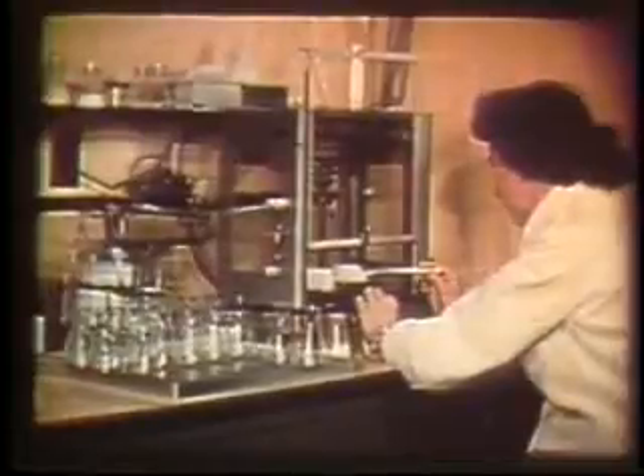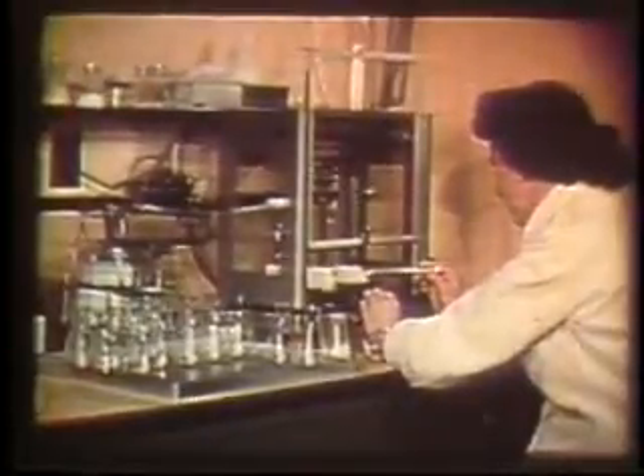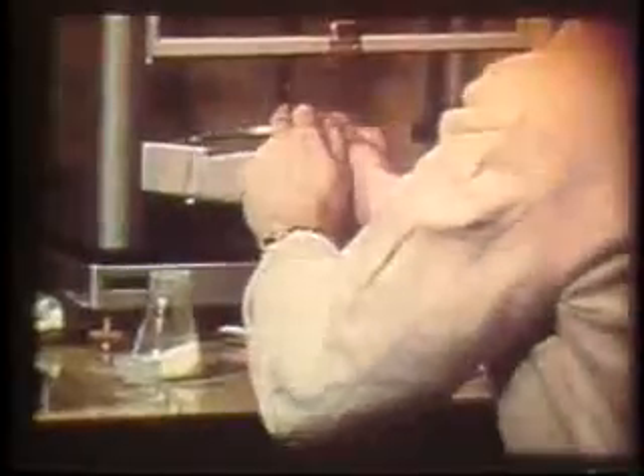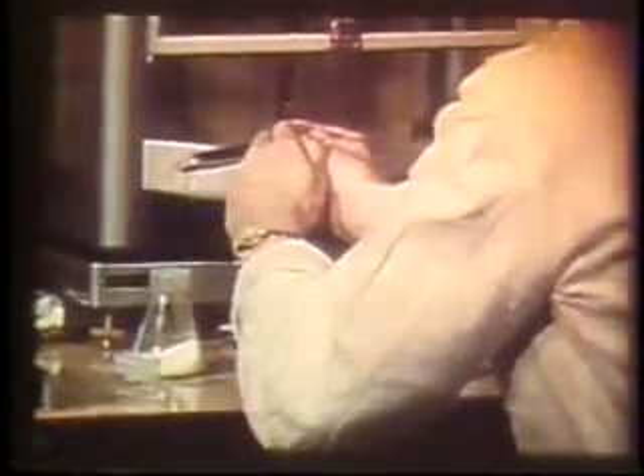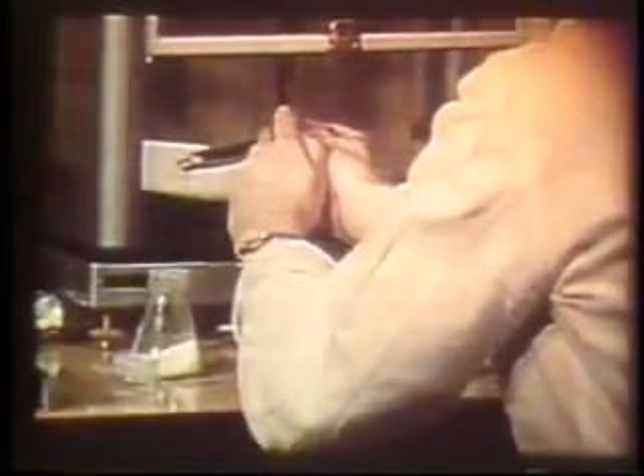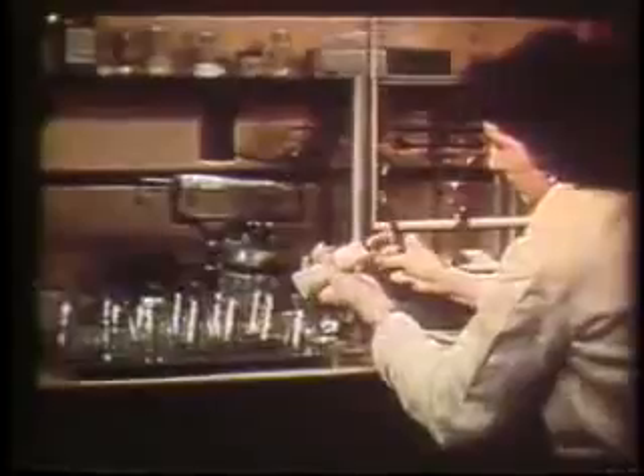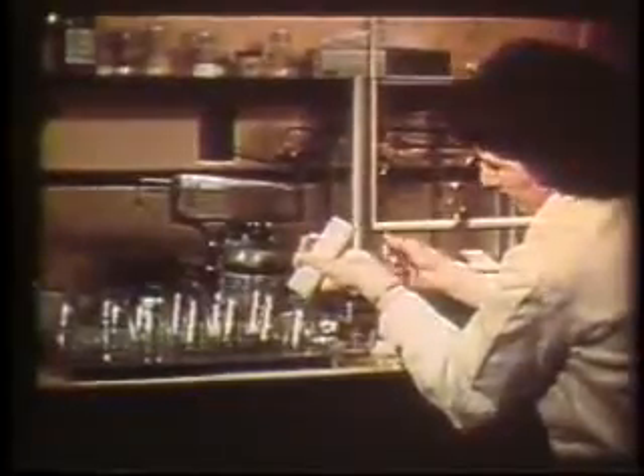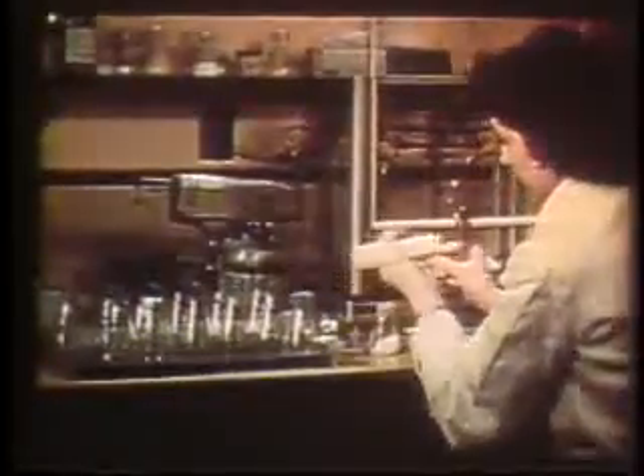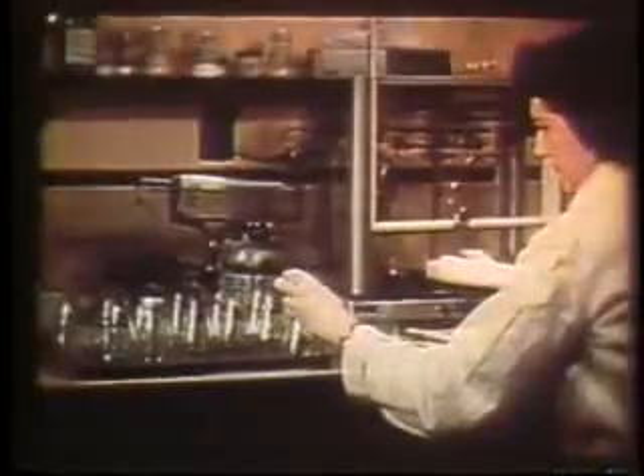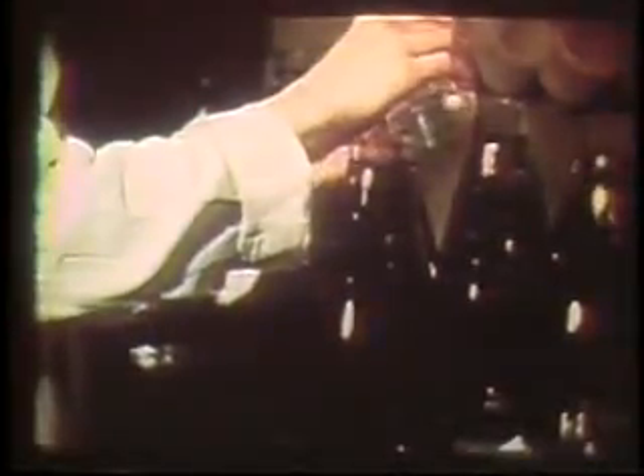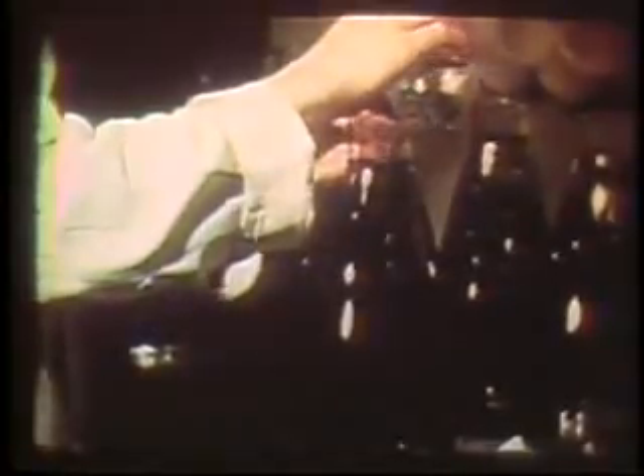The screen material, or phosphor, is carefully mixed and weighed out. Both the composition of the material and the amount used are very critical. A small change here can make a great change in the light output from the screen. The inner surface of the faceplate is again cleaned and lightly etched with a solution of hydrofluoric acid.